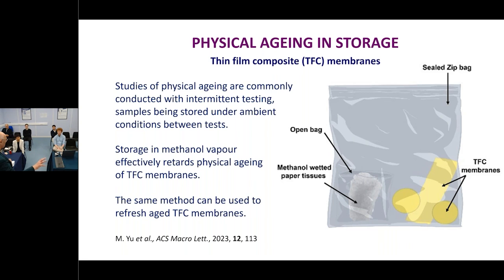Which goes back to, again, what we do in the lab is often not representative of what happens in real life. So if you go to the literature and look at aging studies, what's normally happened is someone's in the lab, they do a permeation measurement on a membrane. Now, they're not going to leave that membrane in that bit of kit for months or years because they need the kit. So they take the membrane out, put it in a drawer, and weeks later, months later, years later, they go back, they measure it again. But in the meantime, that's been sat in the drawer.